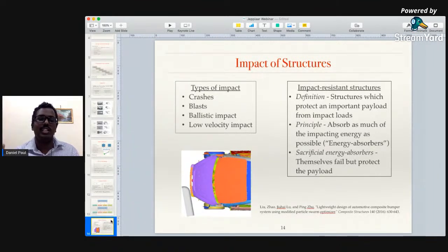So these kinds of low mass, high velocity impacts are called ballistic impact. You can also have low velocity impact, like a tool drop. Even a tool drop in a composite material can be dangerous because it can cause defects inside the material which are not visible to the naked eye. But when such a material, which has been damaged by a tool drop or some very low velocity impact, undergoes fatigue or any other high kind of loading, it can cause extensive and premature damage in the material.